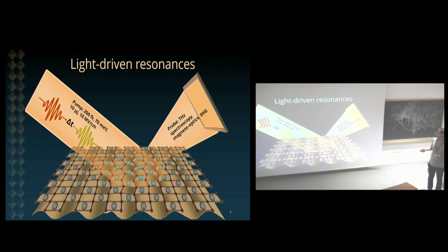So after this pulse has interacted with matter, we come with a second pulse, that's the probe, and we use this to interrogate structural, electronic, magnetic properties of the material and observe their dynamics. So we can control the delay between the pump and the probe, and this allows us to track in time what happens. This is an averaging experiment, right? So you come with the pump, you interrogate with the probe, and you do this again in our lab 1,000 times per second, and you average out your response, and you get rid of a lot of noise. Okay, so that's a little bit the approach.